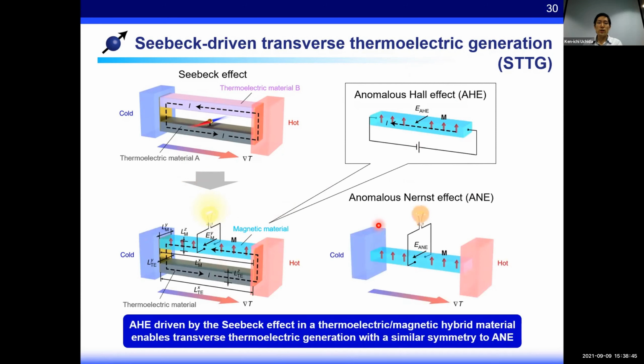As shown in these illustrations, the anomalous Hall effect driven by this Seebeck effect in thermoelectric and magnetic hybrid materials enables the transverse thermoelectric generation with a similar symmetry to the anomalous Nernst effect. We call this phenomenon the Seebeck-driven transverse thermoelectric generation, STTG. Since the Seebeck effect is the driving force, the Seebeck coefficient of the thermoelectric material must be large, and the anomalous Hall angle in the magnetic material must be large.